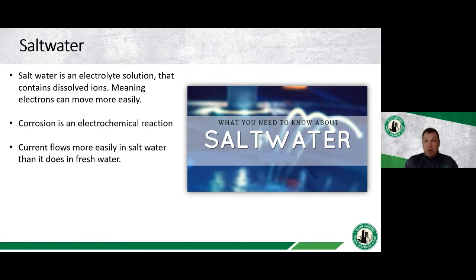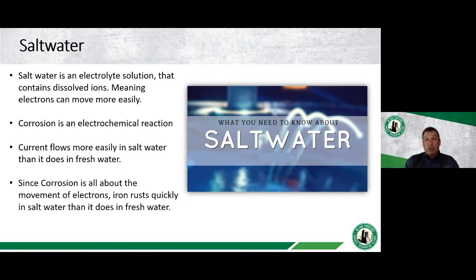Corrosion is an electrochemical reaction. So when we have a lot more ions, or a lower resistivity, basically Ohm's law states that we're going to have a much higher current flow or a higher corrosion rate. So anything, especially our piles that are in a saltwater environment, is going to have a lot more aggressive corrosion taking place, especially because of that tidal surge where we have a lot of oxygen and moisture present.